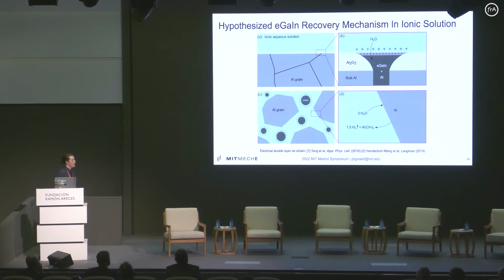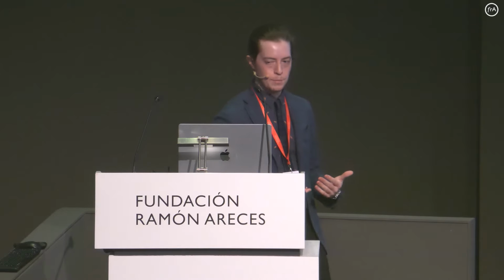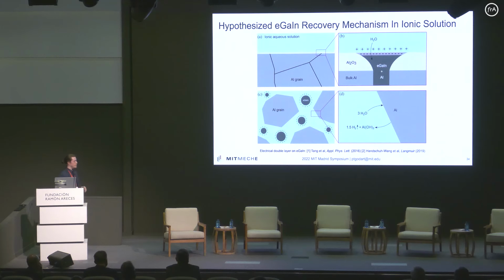And so using this model, we realized that the new challenge was to figure out a way to selectively passivate that gallium water reaction, but allow the aluminum water reaction to proceed. And I discovered a method to do this by modulating just the ionic strength of the solution and controlling a few other factors, like the rate of crystallization of the aluminum hydroxide. But discovered that by doing so, and in this case I'm just using sodium chloride,